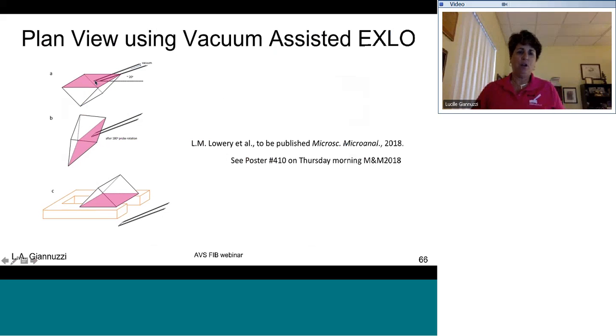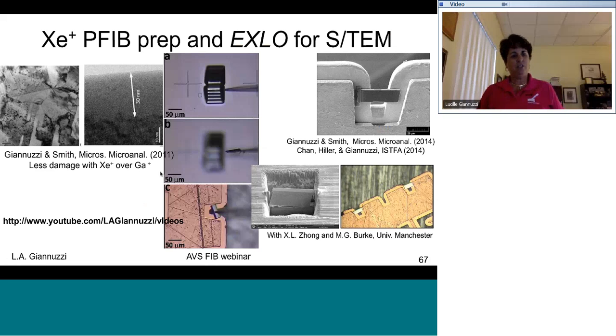Something that did recently, again with the group at San Diego, this is a double hollow probe. Doing plan view analysis, they lifted it out, flipped the sample over 180 degrees, and just placed the probe through the slot, allowing the sample to come to rest on the slot. This only took a couple of minutes to do. And then you can subsequently FIB mill to do your plan view analysis. Again, making larger samples for Xenon plasma FIB is just as easy to do.